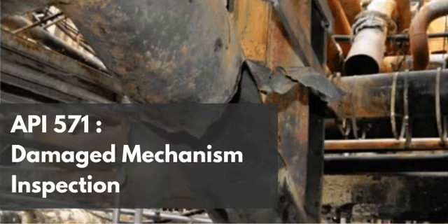Well, think about the microscopic tip of a newly formed crack. When ammonia attacks a microscopic flaw and begins to separate the grain boundaries, there is a massive concentration of stress right at the tip of that microscopic crack. Like a wedge being driven in. Right. Now, in a lower strength, highly ductile steel, something strictly under 70 ksi, the metal right at the crack tip can actually yield. Oh, I see. It microscopically deforms, which blunts the crack tip and safely redistributes the localized stress into the surrounding metal. The crack literally runs out of mechanical energy and stops. That's fascinating. It essentially absorbs the blow by bending slightly at the microscopic level.